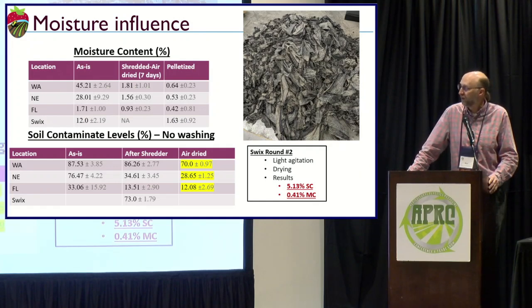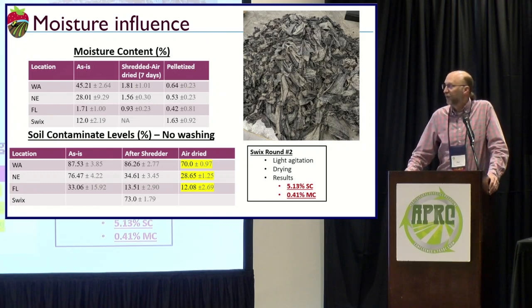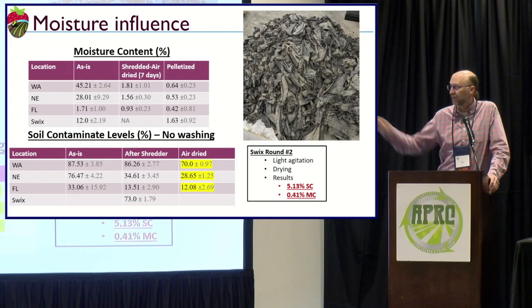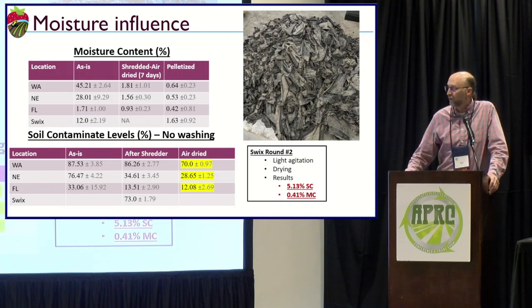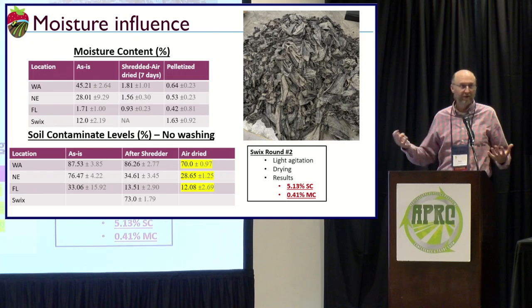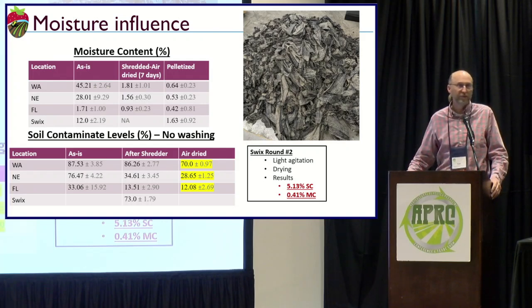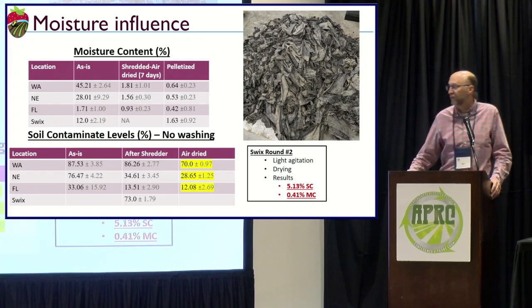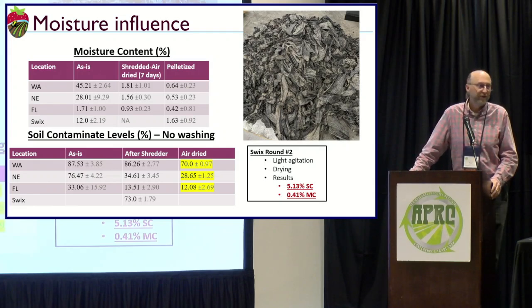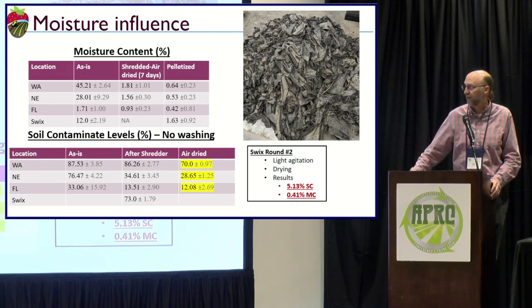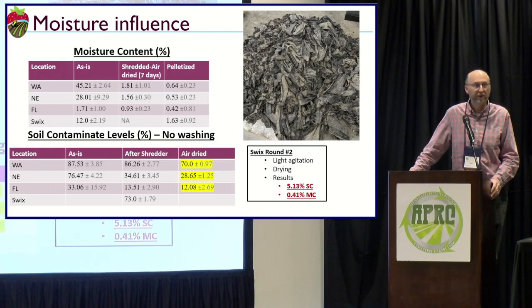The next thing we did is take that dried film and look at how much soil is on there, or you can look at the as-is film and get a soil content. With the Washington material, where it's nice and wet, we saw pretty high soil content levels, 87%, which is really high. Once we air dried it after shredding, we got it down to 70%, but that's still quite a bit of material on there. At the Florida site, we started out with 33% soil contaminants, and then got down to about 12% when air dried.